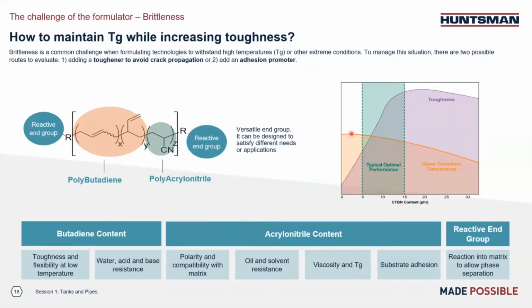But at the same time, we start to see some bad impact on the glass transition temperature. For example, if we're using 15% per 100 parts resin, the toughness improvement is really good, and we start to see some dropping in TG. If we further increase the loading amount to 20%, compared with 15%, the improvement in toughness is very minimal, right? But the TG impact is getting bigger, right? That's why we usually recommend using between 5 to 15%, this kind of sweet spot, as your formulation design.